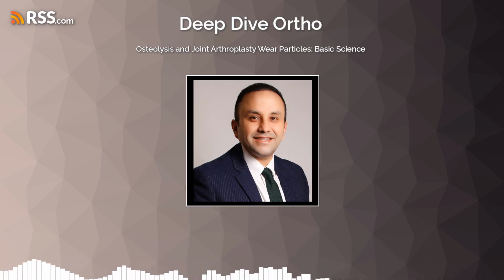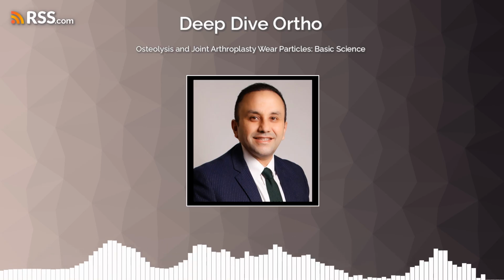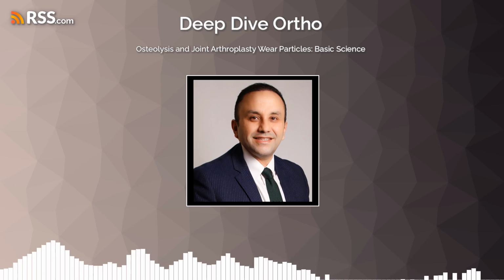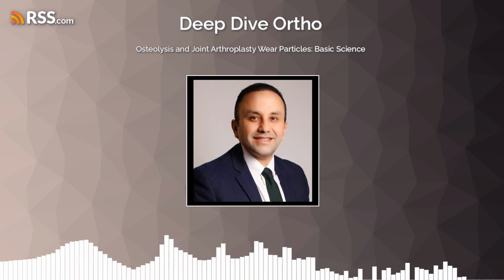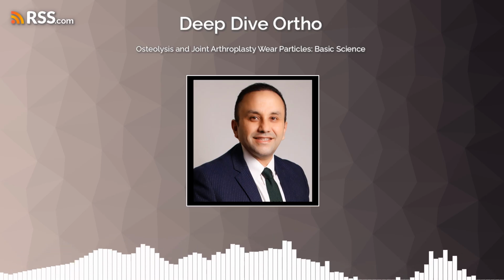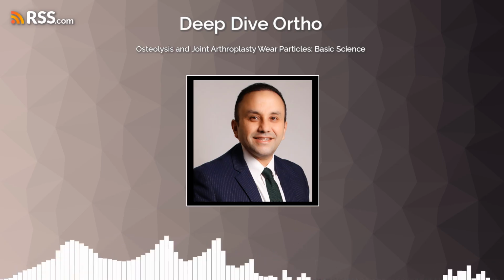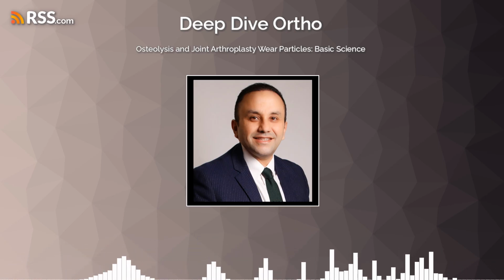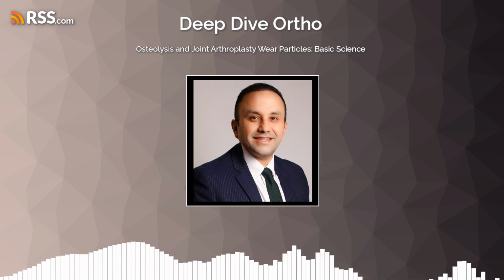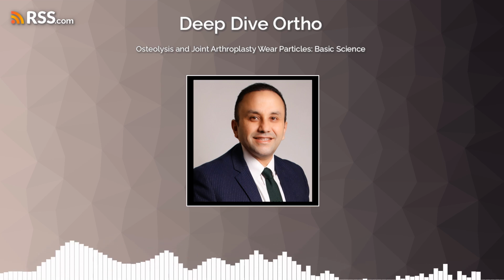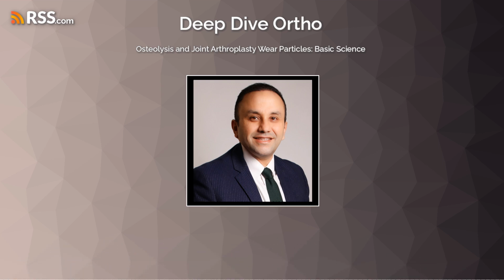The femoral head size is a highly important factor in predicting particle generation. Larger femoral heads, despite offering some advantages in stability, generate a significantly greater volume of wear debris for the same linear wear due to that squared relationship. Wow. This means even a small increase in head radius can lead to a disproportionately large increase in particle volume.